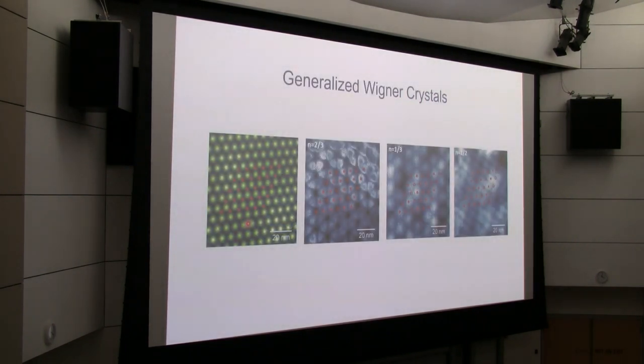So here I show you some images of this generalized Wigner crystal. On the left-hand side, this is a topography image where you can see the Moire superlattice directly. And the red dot illustrates a specific AB stacking site where electrons prefer to sit. And then when we add electrons into the system, say at 2/3 filling, we get an image like here. All the bright region is where the electron sits, and the black region is where you don't have electrons. So if we mark all the bright regions with these filled red dots, you can see they form a lattice and they avoid 1/3 of the possible sites.